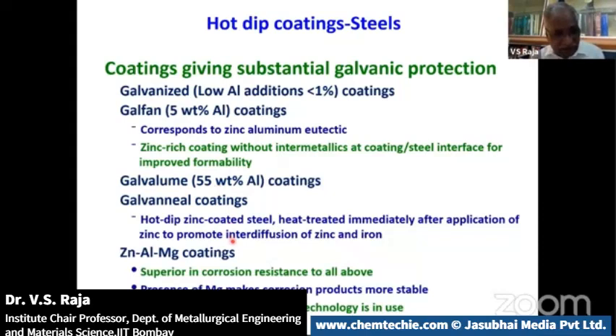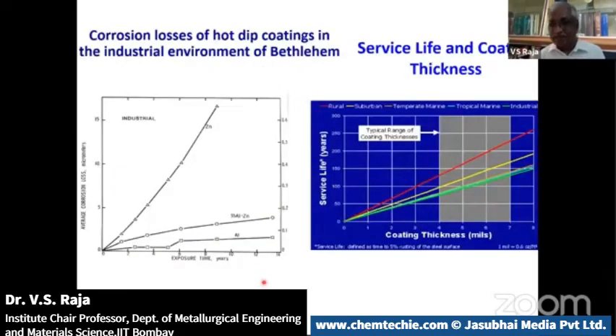For automobiles, they've been talking about it. We talk about zinc, aluminum, magnesium coating. It gives you 5 to 6 times more corrosion resistance than this one by adding aluminum and magnesium. Superior coatings are being developed by changing the metallurgical properties. Again, I'm just giving you only illustrations. I don't have time to go into details. One of the important things when we talk about zinc coatings is that the service life of these zinc coatings is related to coating thickness, right? When the coating thickness increases, the service life increases. But that is very interesting that we know about it.